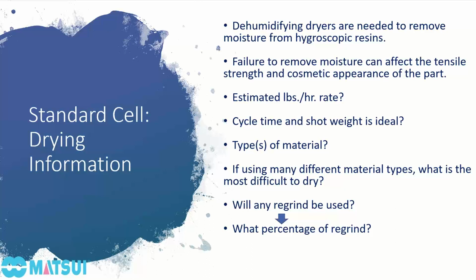Also, will any regrind be used? Are you going to be reprocessing any of the regrind? And if so, what percentage of regrind? Now, it's not so much that regrind is more difficult to dry. It can be if you leave it in storage for a long period of time, where it can reabsorb moisture. And sometimes if the beginning or initial moisture content is too high, it can't even be dried if it's exposed too long. But the main